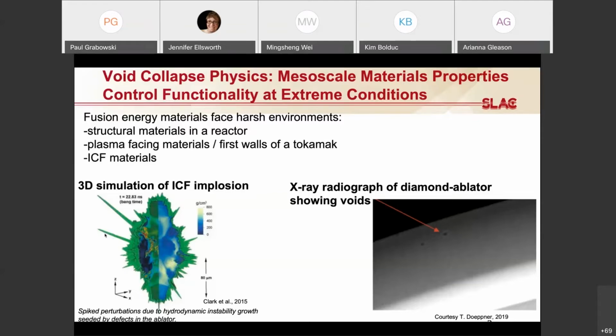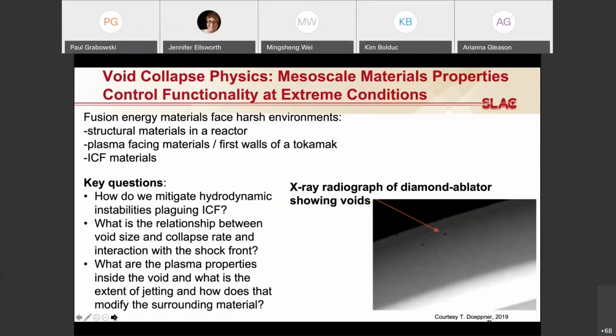There are many different causes of these instabilities and their growth, but one that is considered in this community is voids and defects in the material. Shown on the right here is a radiograph of a diamond ablator used in a capsule, and you can see some of these features, not necessarily desirable aspects in the sample, that could be potential seeds for these hydrodynamic instabilities. So we want to look at how this process actually takes place.